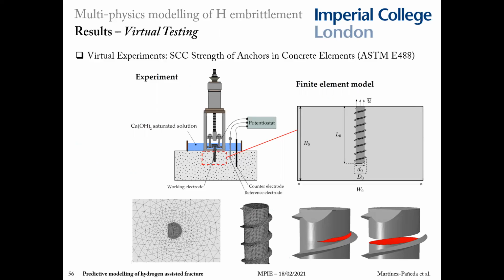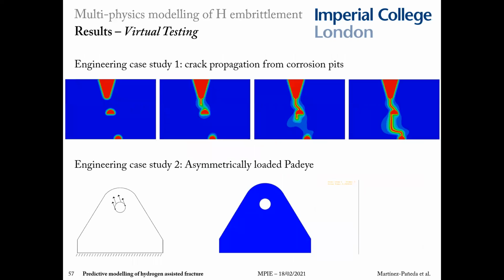So for example, bolt cracking is a big problem in hydrogen embrittlement. And here you can see an experiment to measure the strength of a steel screw anchored to a concrete slab. And this is a problem that involves also contact between two materials, as you can see here. The complete failure of the screw, as you can see in the slide, can be captured in our virtual experiment. So one can really precisely and effectively run those virtual experiments. And these agreements with experiments gave us the confidence to go beyond the lab into field applications, aiming at enabling the virtual testing paradigm that I mentioned before for hydrogen sensitive applications.